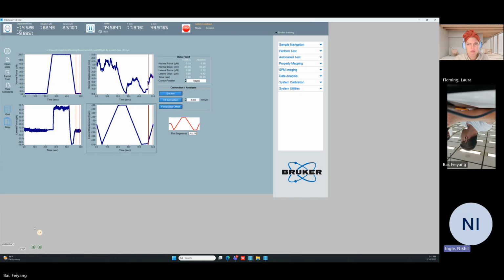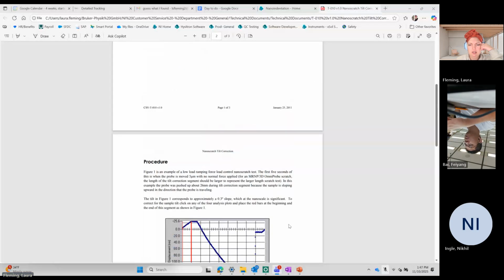I think we can try a scratch test on a quartz sample. I would not. You can, but I would not. You're going to blunt the probe. Quartz is pretty hard. You're welcome to try that. It's just that you're not really looking for data right now on the fused quartz, so you're doing nothing but risking your probe. If you put in too high of a force, and we don't know what a good force is, you run the risk of causing blunting.